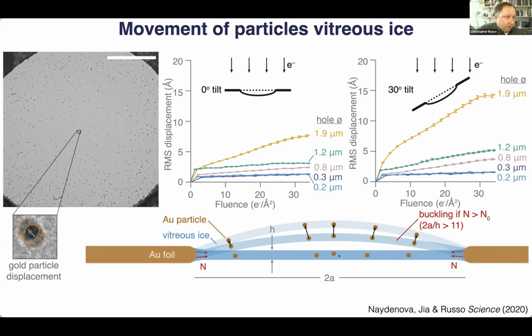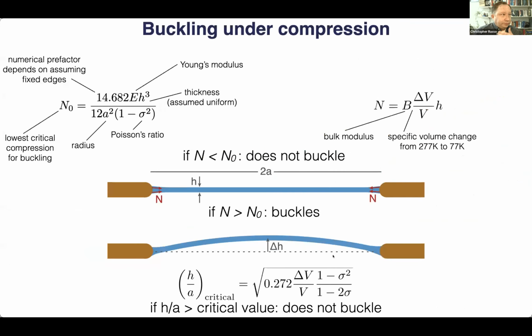And so we tried to work out exactly the details of how one might explain this. And so here's our theory of this buckling. And essentially, it's a simple thin film mechanics problem. If you have a stiff material suspended across a hole and you apply a normal force to the edges, at what point does the strain get so high that you actually buckle the material in order to relieve it? And it depends, of course, on the Young's modulus of the material and the Poisson's ratio. And there is some critical number above which this material will actually buckle.